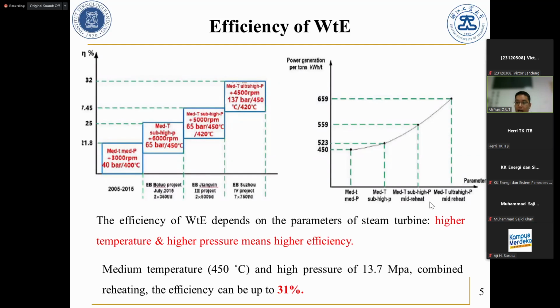So use the middle temperature and high pressure. It will be the maximum setting. So the medium temperature, such as 450 centigrade, and high pressure, 13.7 megapascal. Combined with reheating, the efficiency can go up to 31%. In China, the industrial efficiency is roughly 25%. So it's similar to all incinerators.